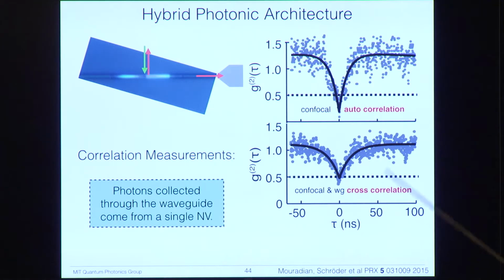We also did what we call an autocorrelation measurement. That's to show that the photons that we collect really come from the NV center. Because the NV is a two-level system, it can't emit two photons at once. So if we time tag all our photon arrivals and then correlate those signals, we expect to see a dip at zero because there can never be two photons that arrive at the same time. So a correlation between collect half here and half there, there'll never be any that arrive at the same time. When we do a confocal autocorrelation, so that's collecting the normal way from the top, we see, as we expect, a big dip at zero. When we do a cross correlation between the photons we collect from the top and the photons we collect through the waveguide, we still see a dip, but the dip is reduced.